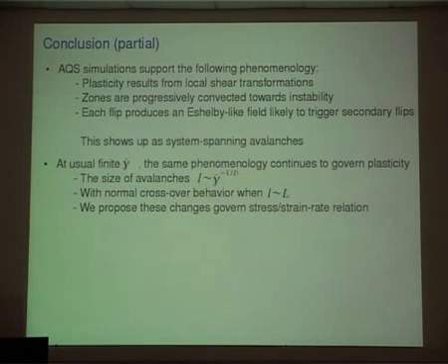And in fact, it's clearly something which is absolutely determinant, which controls the plastic flow of this material up to experimental strain rates, and very possibly is responsible for the shear banding instability. It is not clear whether it is or not responsible for the shear banding instability, but it is now a very good candidate. I mean, this Eshelby mechanism is a very good candidate to account for that.